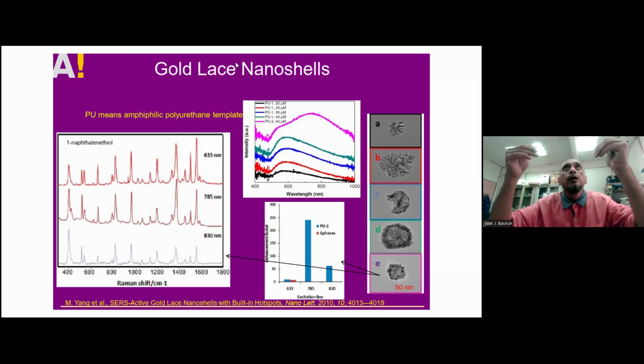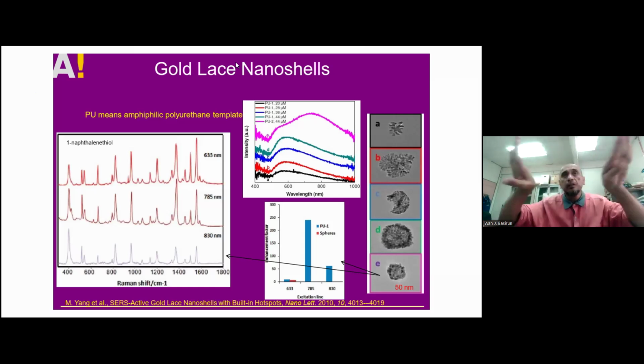So when you prepare a colloidal solution of gold nanoparticles or silver nanoparticles, you must add a certain amount of surfactant. That surfactant will separate the nanoparticles from being aggregated. So that is the strategy. You can actually check without the surfactant and with surfactant, because the function of surfactant is basically to separate and to disperse these nanoparticles from joining up together. That's one strategy. But the amount of surfactant you have to add is just a small amount.